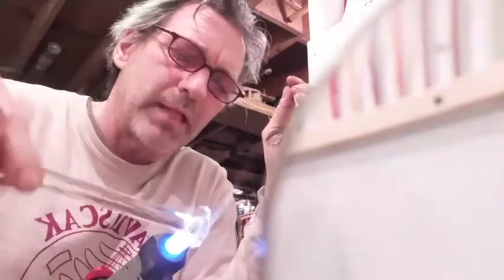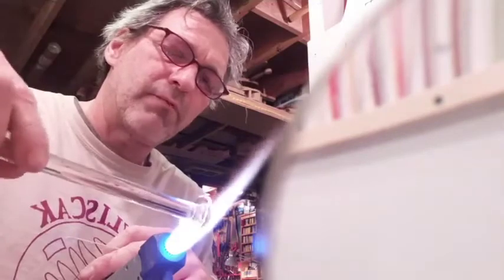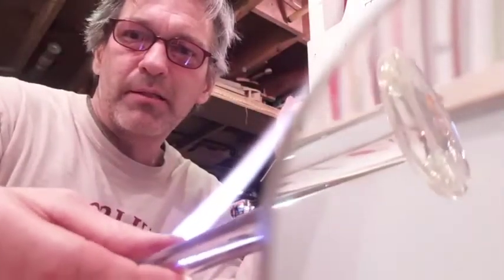Now, I'm going to heat that so it doesn't get too cold. Cold is a relative term when you're working with glass. I want this stuff to stay relatively hot, like 1500 degrees, so it's just about ready to start moving with gravity if I were to stop it from spinning. If it's colder than that, it's going to get very frozen and not want to move. And then this old style glass will crack. It started to melt in those little stamen.